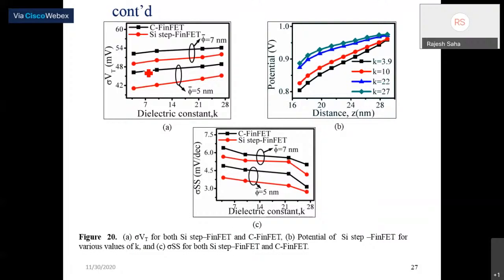We have done another analysis. We did a comparative study between conventional and silicon step devices in terms of the dielectric constant. We considered only two gate sizes, 7 and 5 nanometer. We observed that as the dielectric constant of the gate material increases, the variation in the threshold voltage also increases. But due to better gate control, the step device shows less variation in the threshold voltage compared to the conventional devices.